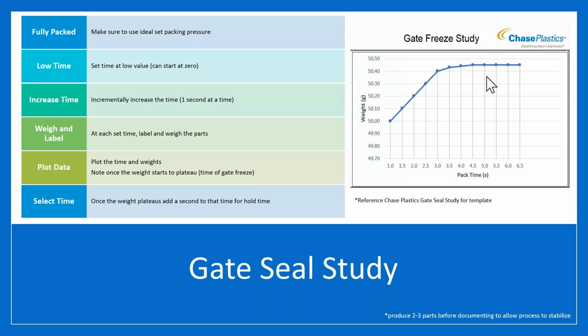I think you're better off doing some iterative work on fill simulation to try and balance those. But from there, if you have two wildly different gate sizes and you're then doing your gate freeze study, you have to pack. So when you're doing how much volume, you use your first to fill. When you're doing how long do I pack for, you're doing your last to freeze. That's the only way you can ensure that all of those cavities are at freeze off. You're going to make some really pretty runner systems for the cavities that freeze off first, but you have to do it that way, or else you're going to have backflow out of the gates that freeze last.